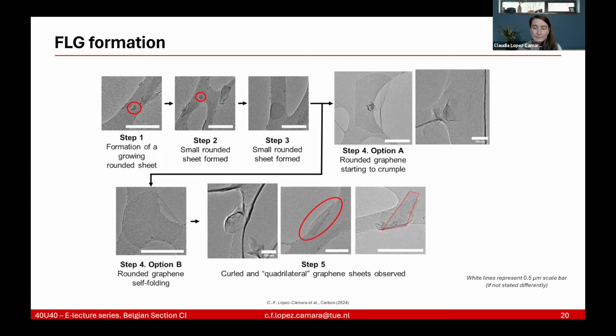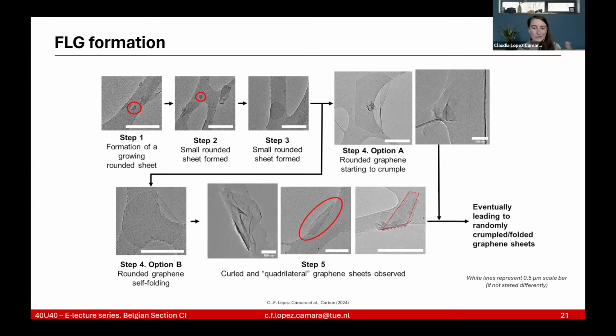And we observed that. However, as I mentioned, perhaps at some point earlier, when we get into the filter, the graphene is already very crumpled. And therefore, that means that either way, it leads to randomly crumpled and folded graphene sheets.